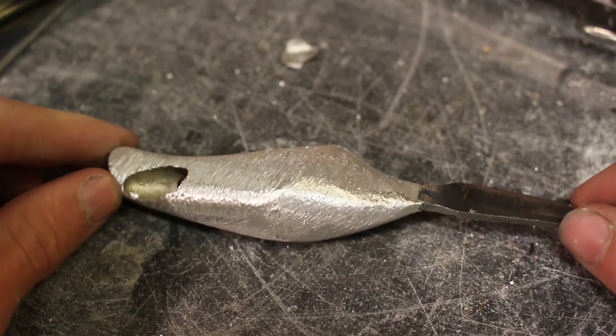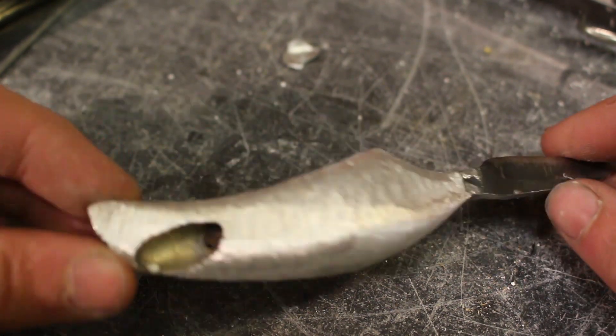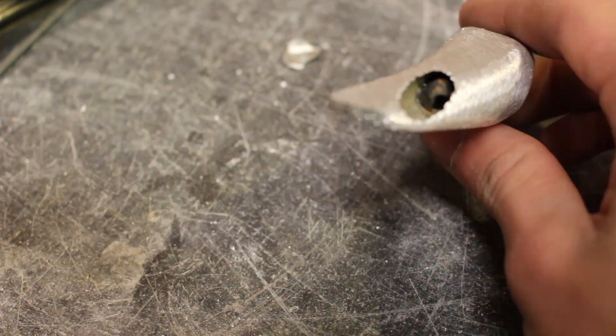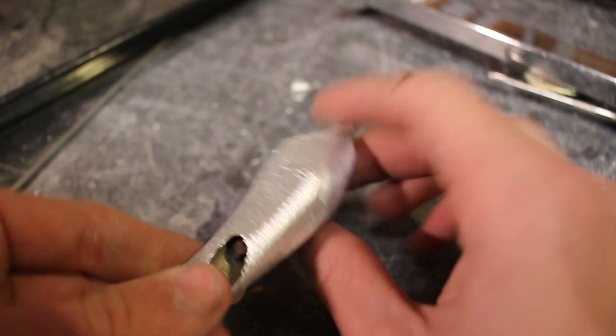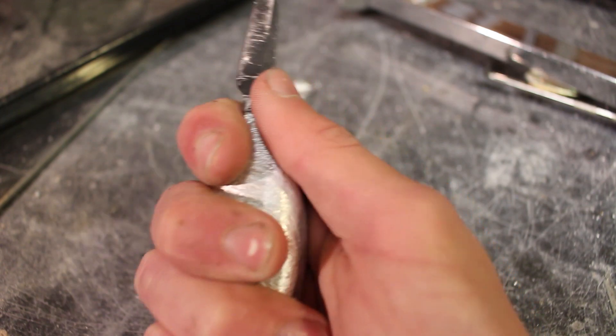Unfortunately as I cast the knife handle there was still a bit of oil left on it and that created a lot of gases as it boiled off and this created a void around the handle inside, and that was uncovered when I started shaping the knife. This could have been quite easily avoided if I'd been less lazy and had cleaned off the handle using spirits. Unfortunately I was lazy and now the void is here for good.